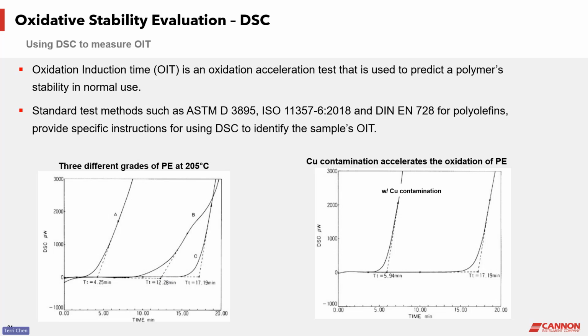The figure on the right side shows that copper contamination could significantly accelerate the oxidation of polyethylene. With just a small amount of copper contamination in PE, its OIT is observed to be significantly shortened from the normal 17 minutes to less than 6 minutes at the measurement temperature.